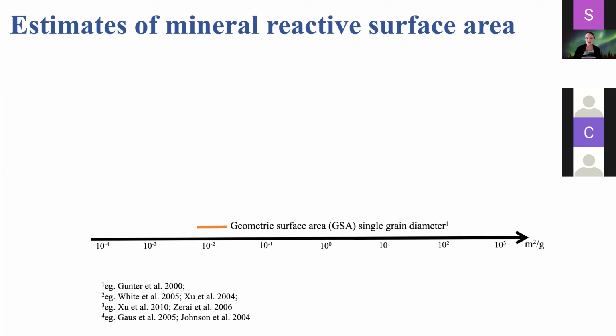So the simplest approach is to use a geometric surface area where you say that everything is a sphere of a single grain diameter. Well, the problem with this is that clay minerals are inherently different than other minerals and have much larger surface areas. We account for this by using two surface areas, one for clay minerals and one for all other minerals.